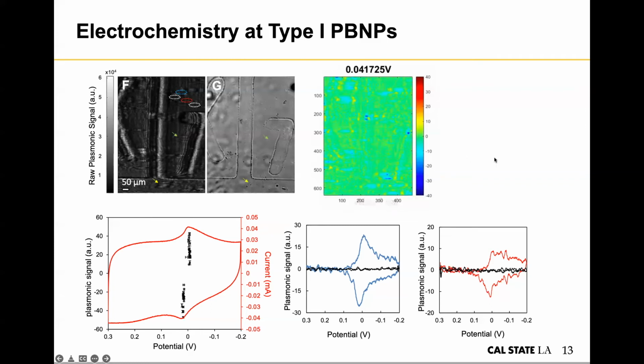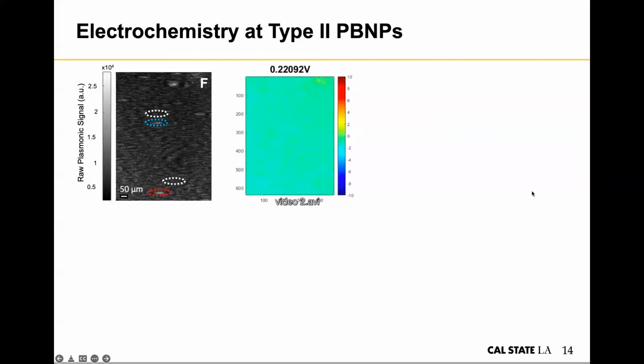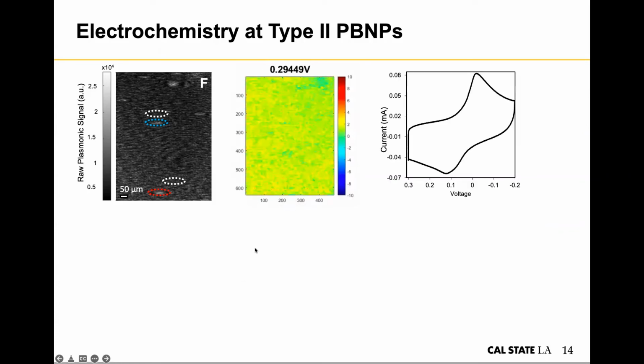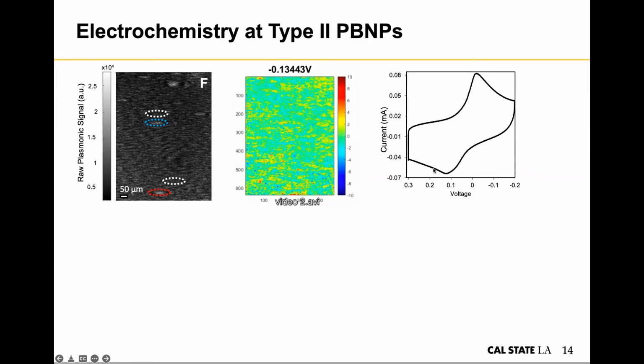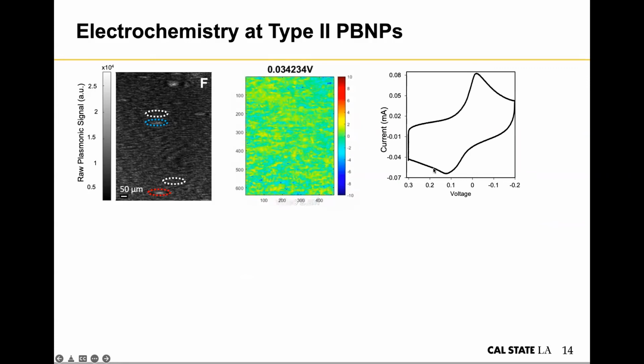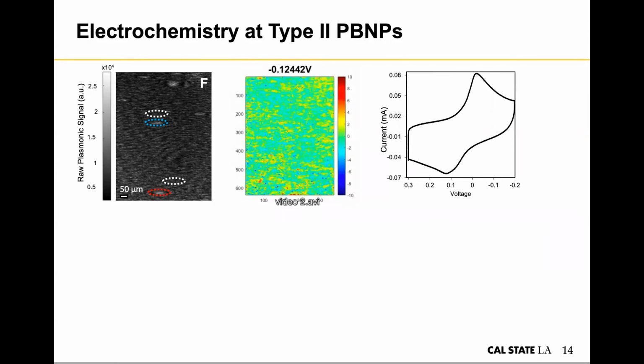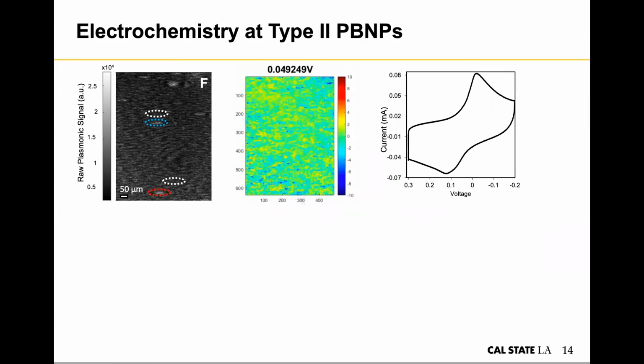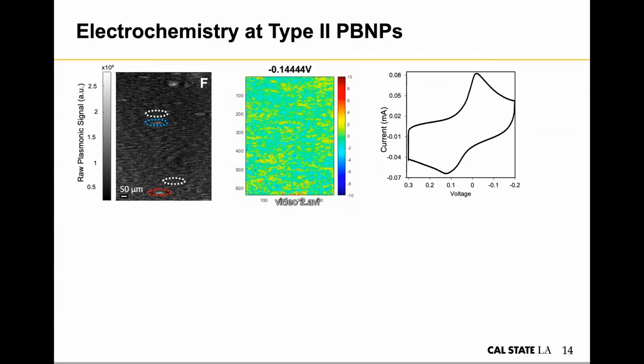Now with type 2, we expected to see something special because those particles are more cubic in shape, but unfortunately what we see is a very weak signal. Here's the example. Here is the potentiostat CV, and you can see that it deviated from the symmetrical shape, which we can expect from a thin layer of Prussian blue already coated on the electrode surface.